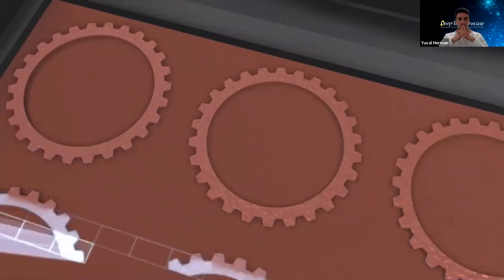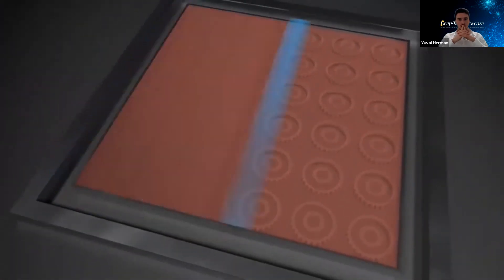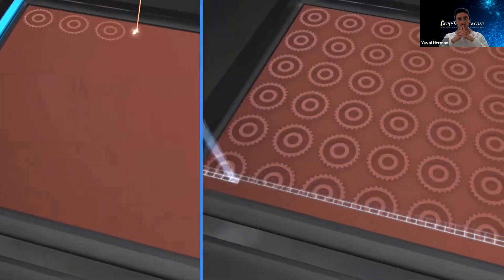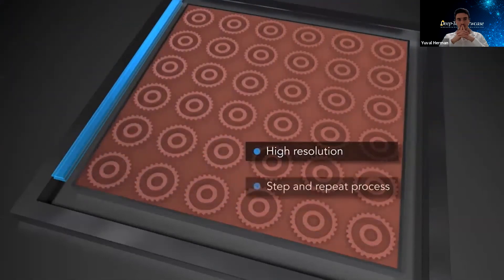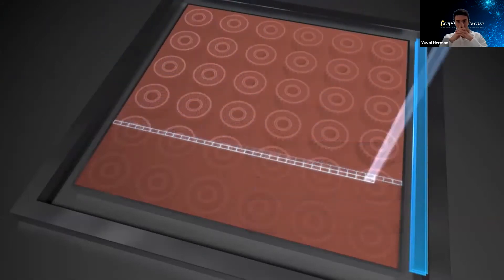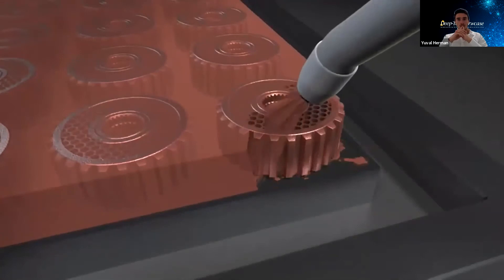The light modulated image is projected on a powder bed and melts a large area of the powder layer with extreme high resolution. A step and repeat process completes the powder bed layer, and successive layers of powder are added and printed. When compared to traditional infrared-based 3D printing, area printing can produce parts at a speed that is 100 times faster. Blue laser technology enables this new area printing method for metal parts, providing a step and repeat process with extremely high speed printing and ultimate efficiency due to high absorption in the blue. With the increased production speed, metal 3D area printing becomes a much more cost-effective solution for precision printing of small and large parts alike.